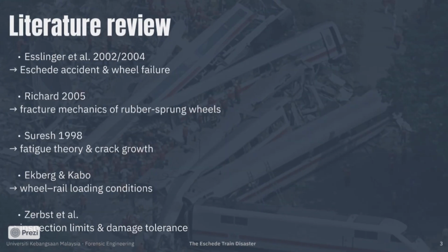Our literature review is based on a few key sources. Esslinger and co-authors provide the main technical analysis of the Eschede wheel failure and identify fatigue crack growth as the governing mechanism. Richard adds fracture mechanics insights and explains why rubber-sprung wheels can develop critical stress concentrations. Suresh provides the fundamental fatigue framework. Cracks can initiate and grow under cyclic stresses even below yield strength over many cycles. Ekberg and Kabo describe realistic railway wheel loading. Rolling contact combined with bending and vibration creates a fatigue-critical environment. Finally, Zerbst and colleagues highlight why inspection strategies must be linked to crack growth and detectability, otherwise critical defects can be missed. These are our main references for the technical explanation and the forensic interpretation.